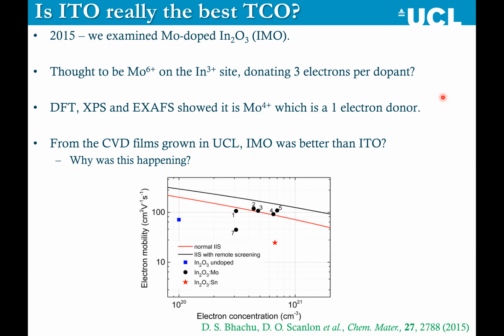So we did some density functional theory calculations, we did some XPS experiments and some XAS experiments at the Diamond Light Source synchrotron, and we showed that it's actually molybdenum in the 4+ oxidation state, which is a 1 electron donor, meaning that it acts quite similarly to tin doping in indium oxide. So in ITO, tin is 4+, so adds 1 extra electron. And in this system, which we're calling IMO, obviously it's a 1 electron donor also.